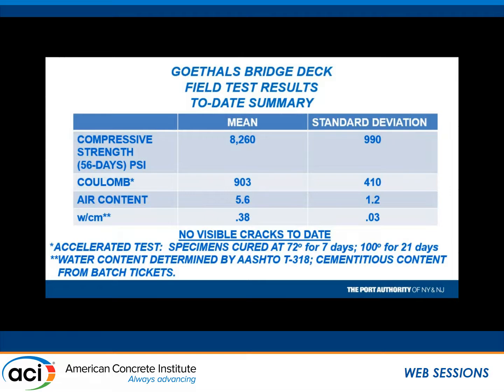And we certainly use the Coulomb test for acceptance, the rapid chloride permeability test, and we do that with every sample of concrete. And that's another test people say you can't use for quality acceptance. Well, why not? We do it every time, every day. And if it doesn't work, then how come somebody didn't come and sue us? We had one guy that threatened to sue us, and then he had second thoughts, and he showed up with his lawyer and admitted that he didn't put the fly ash into the mix, okay, because the Coulomb numbers were so high. So I think those two things are important to do.